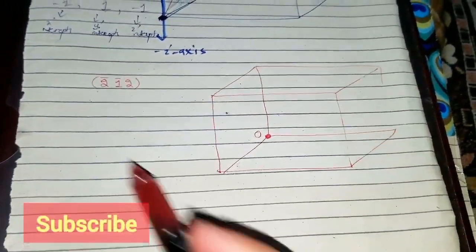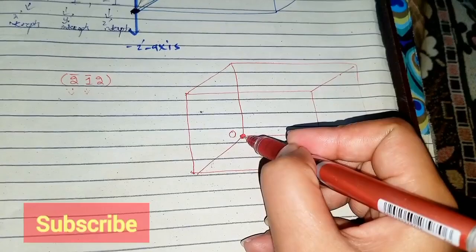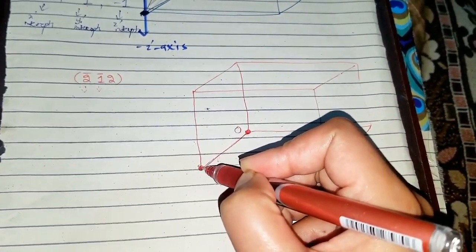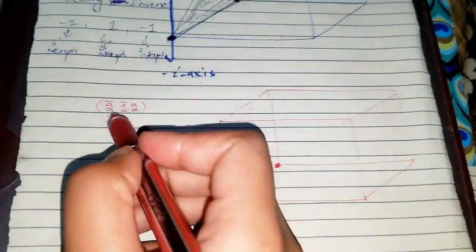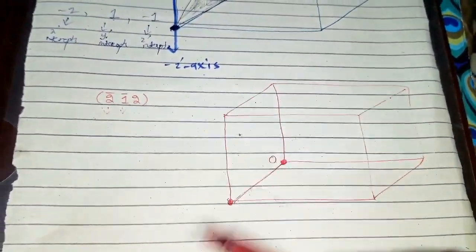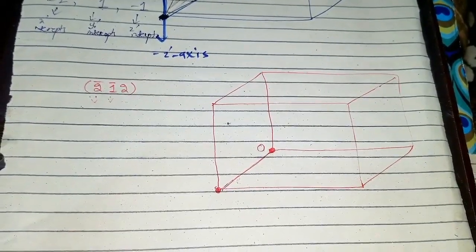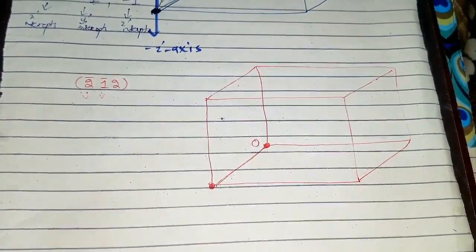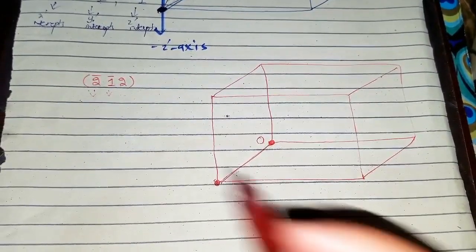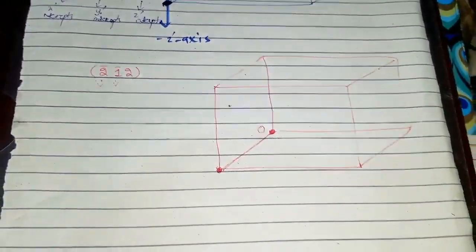Alright, and we have to shift the origin. The x index is negative and the y index is negative, so starting from the all positive origin we have to shift the origin 1 unit along the x direction, since the x index was negative. That shifting is always done by 1 unit, regardless of the numerical values. These numerical values don't affect the position of the origin that we select. The shifting of the origin is always done by 1 unit, and the negative nature only matters.